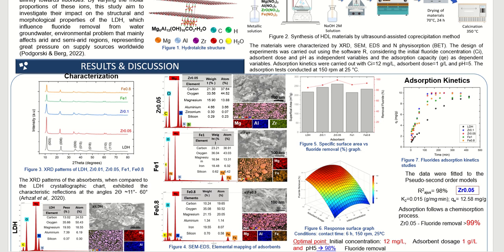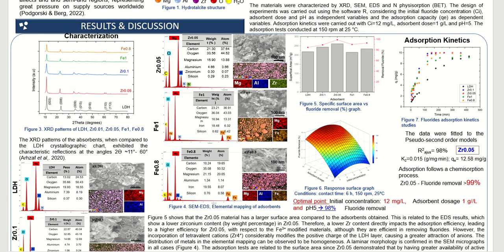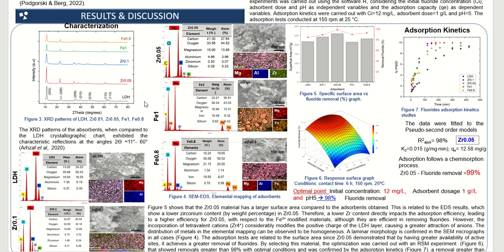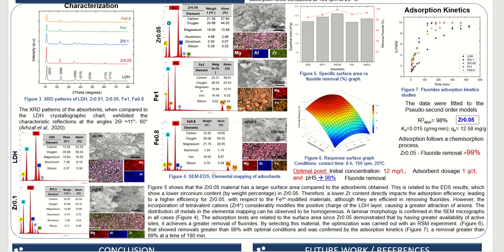We move on to the discussion and results section, in which the results of the characterization of the materials are presented, where in the X-ray diffraction, Figure 3, the characteristic reflections of the hydrotalcite phase are observed, independently of the proportion of zirconium and iron. However, the crystallinity is affected by the greater quantity of zirconium and the incorporation of iron. It is observed that the crystallinity decreases, and this effect in the case of zirconium can be attributed to the formation of another phase, possibly zirconium oxides, which is confirmed by the result of the EDS and elemental mapping,